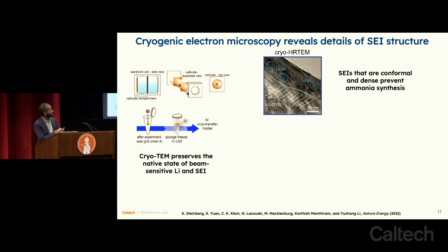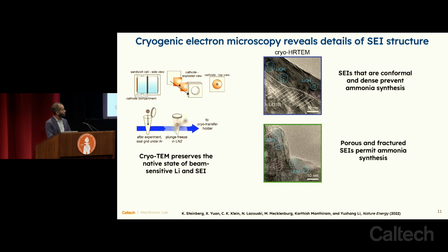When the solid electrolyte interface is conformal, as I'm showing here, and rather dense, it actually entirely stops reactivity in the system. The lithium metal can no longer access nitrogen or the proton donor to be able to make ammonia. When instead you can make a fractured solid electrolyte interface of the sort that I'm showing here, which is porous and disorganized, you can now activate lithium metal to be able to drive this conversion of nitrogen to ammonia.